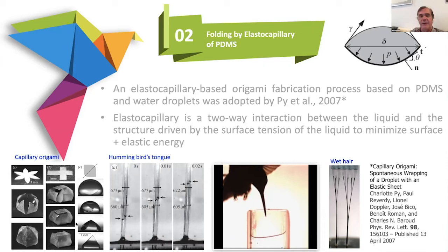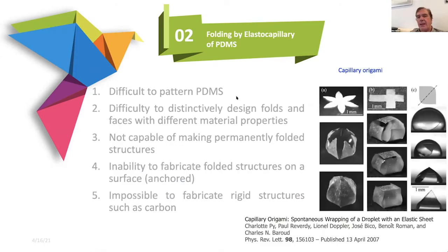But there are quite a few shortcomings to this approach. What are these shortcomings and what could be done next? Well, number one, it's difficult to pattern PDMS. You can make these shapes, but this is not a photoresist, so you stay in quite large devices. Secondly, it's difficult to distinguish between the folds and the faces. These are faces, and for the fold here, you would like it to have another material property than PDMS in the faces. In the Py et al. approach, that's not there. There's really little difference, actually none, between this fold area and the faces.